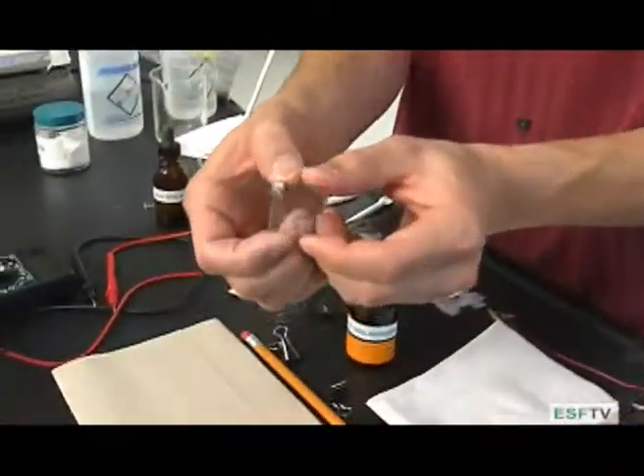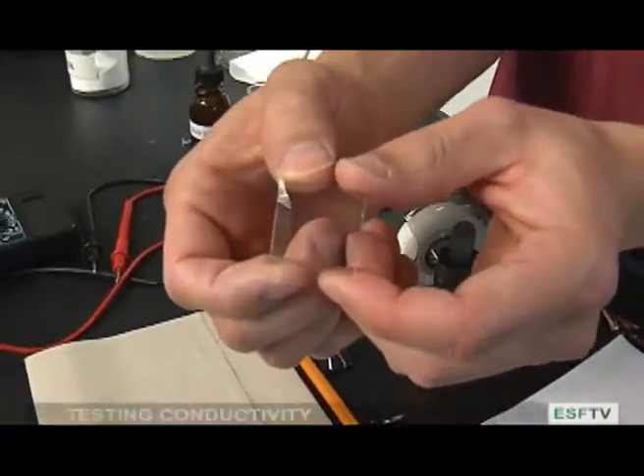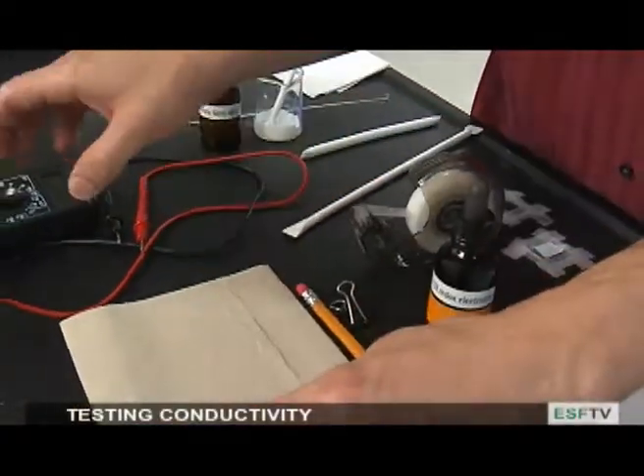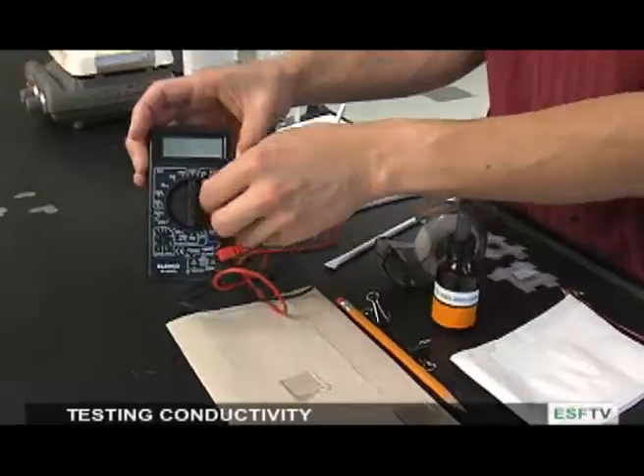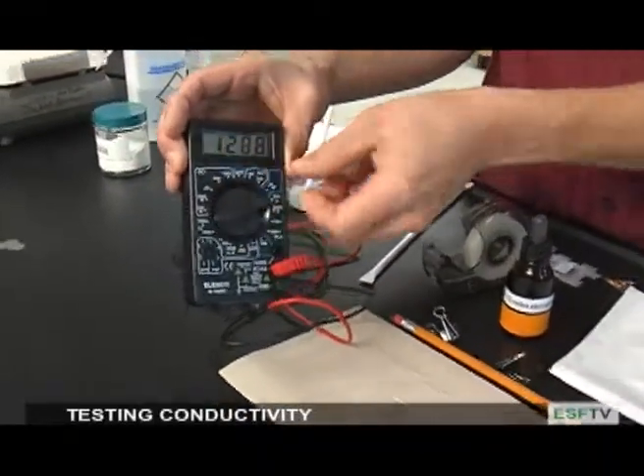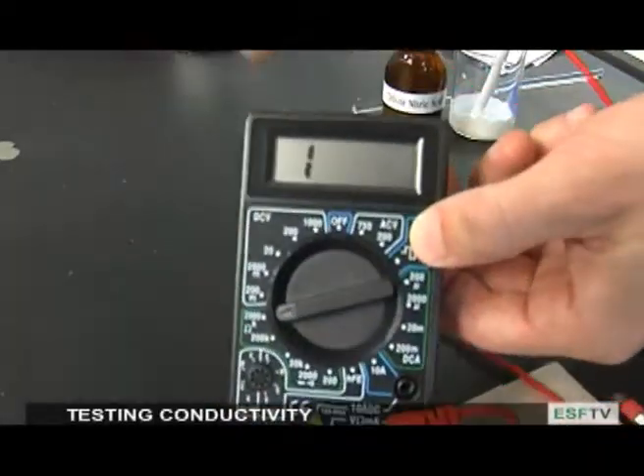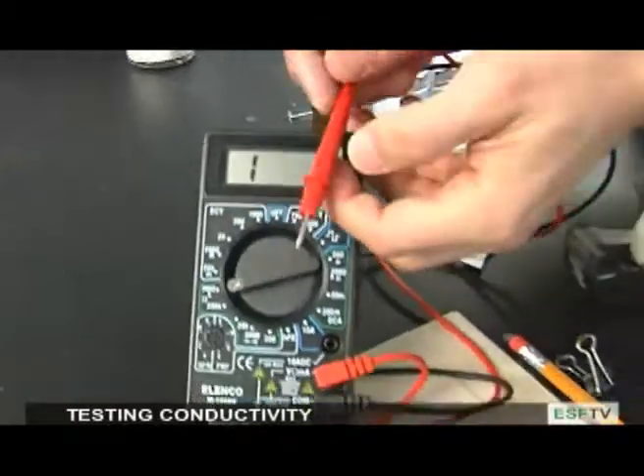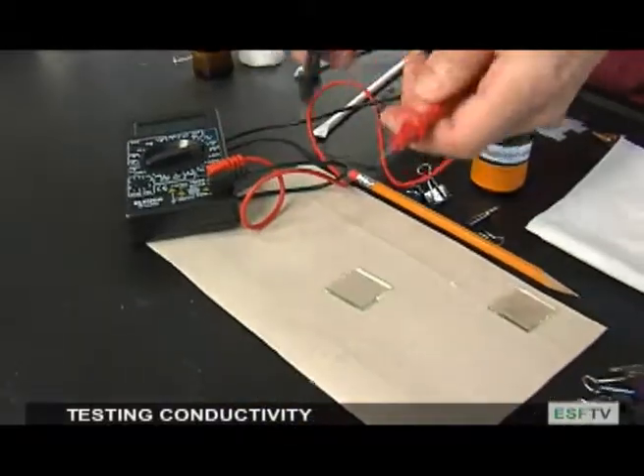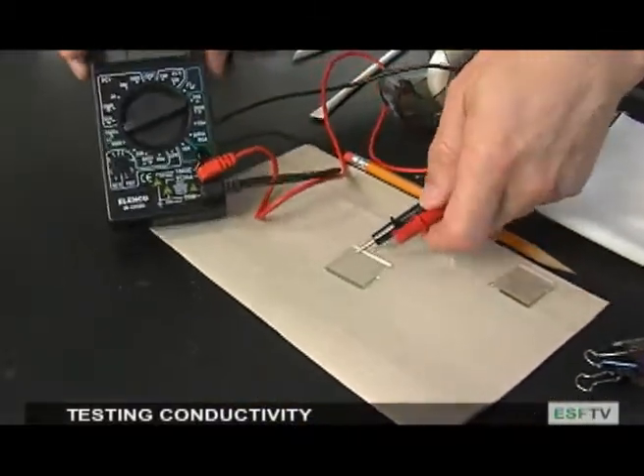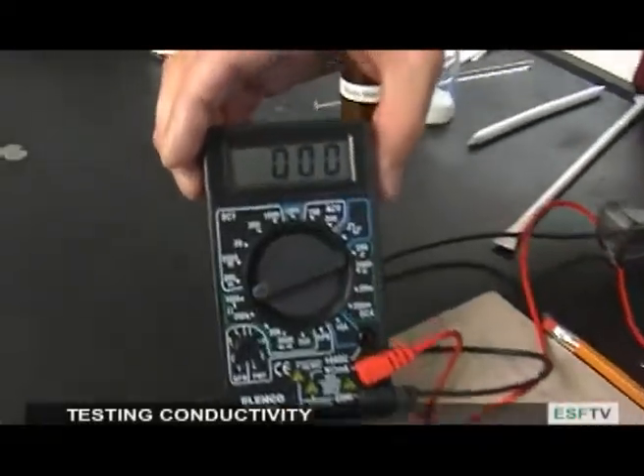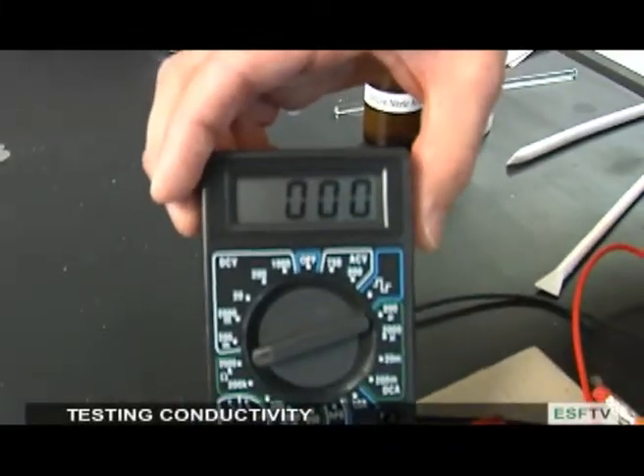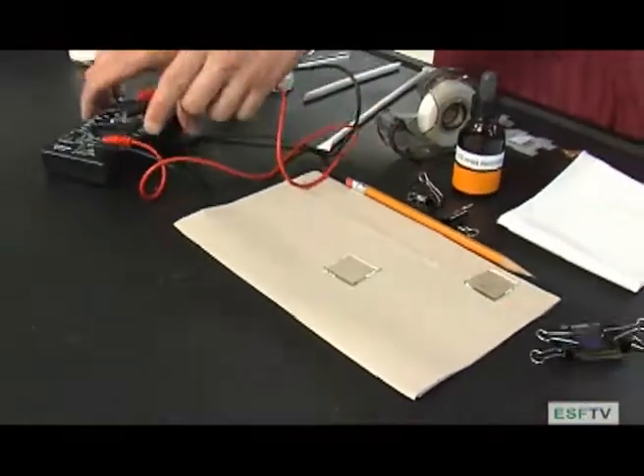So we're going to start with a piece of indium-doped tin oxide glass. This looks like normal glass, but it actually has a conductive coating on it. To find out what side the coating is on, we're going to use a multimeter set to resistance. If we have the correct side, we'll see that the resistance goes to zero. So let's take a look. And we can see that the resistance now says zero, so we have the correct side facing up.